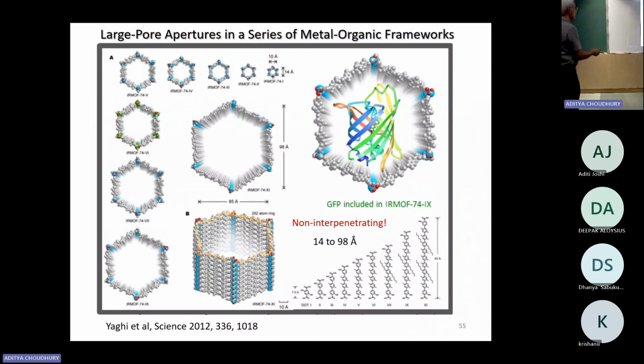Okay, the next one, he made non-interpenetrating MOFs, and that was published in Science a couple of years ago. He started making this type of pores, non-interpenetrating, from 14 angstrom diameter up to 85 angstrom, and then he made it non-interpenetrating up to 98.